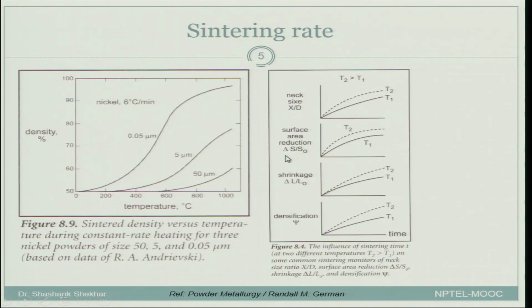Surface area reduction. That was the most important driving force, surface area reduction. So, that is also shown here on the y axis, delta S by S naught. This is the amount of surface area that has changed, relative to the initial surface area, and again it is shown with time. At higher temperature it will reduce faster and reach a much larger saturation value. At lower temperature it will reduce at a lower rate and reach a lower saturation value, and again we see that the initial rate is higher than during the later stages.